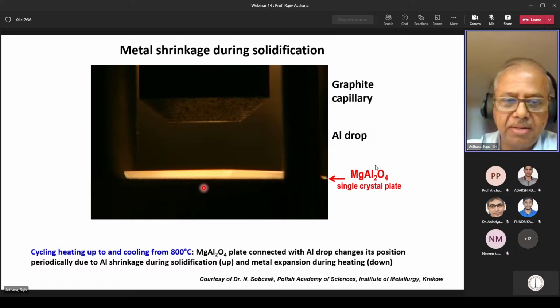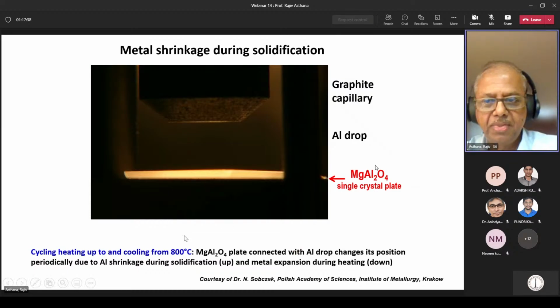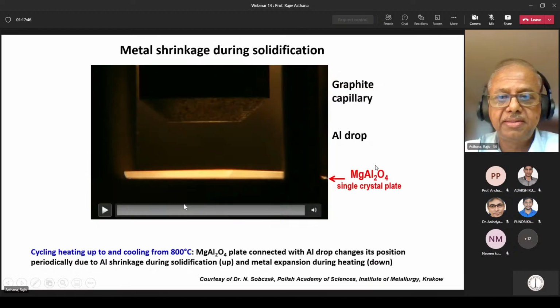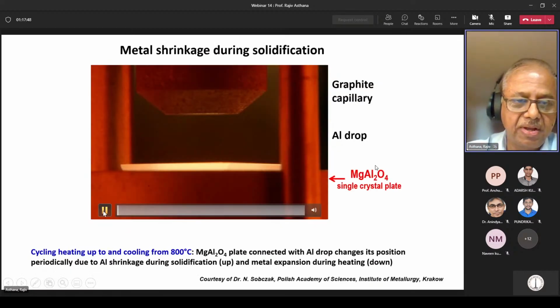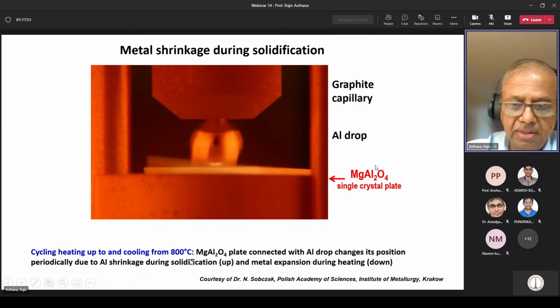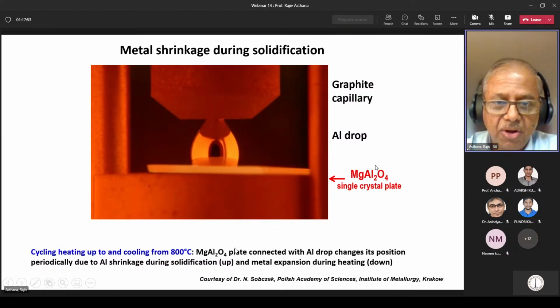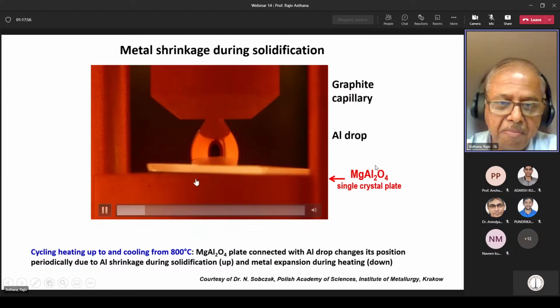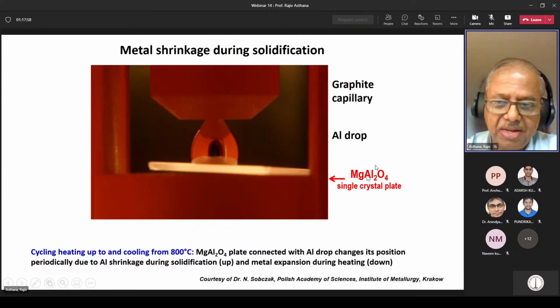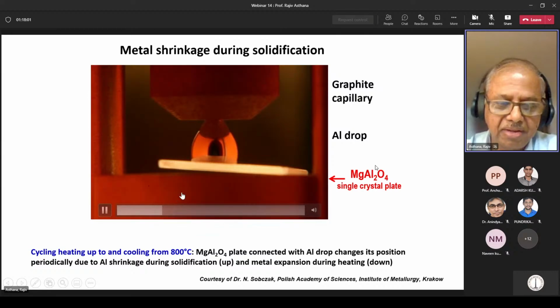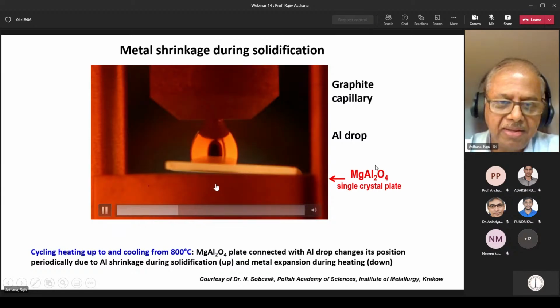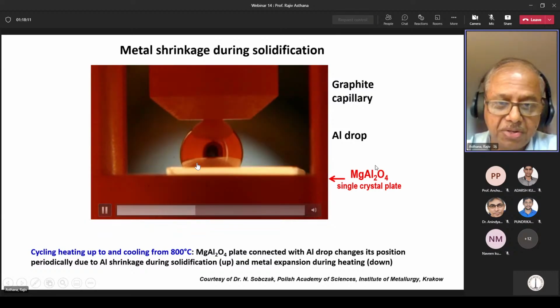Here you're looking at the system where you have solidification shrinkage showing its effect. So when you heat the system, the plate, this is magnesium aluminum oxide plate, it comes down when you are heating the thing because the liquid is expanding. You can see it coming down here because of expansion, but the adhesion stays very good between the two.